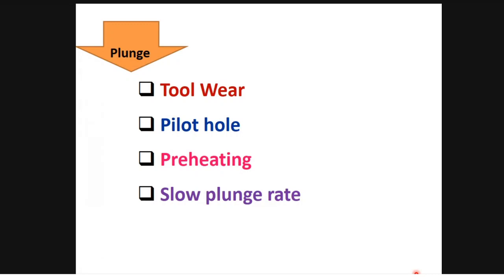And then preheating, as Dr. Gaurav Rao pointed out, you can use what's called thermal stir process, preheating. He also demonstrated at room temperature, 300 degrees centigrade preheating, and 600 degrees preheating. At 300 degrees preheating, the joint performance was good. So preheating is one method.